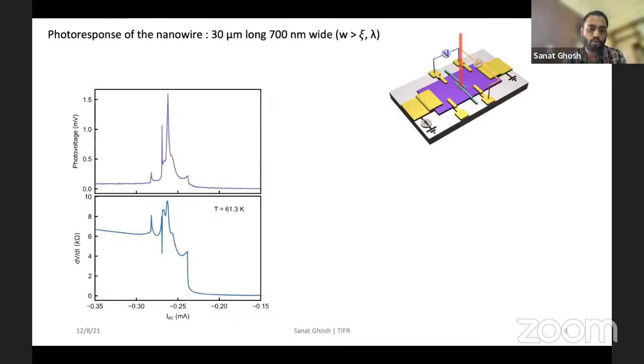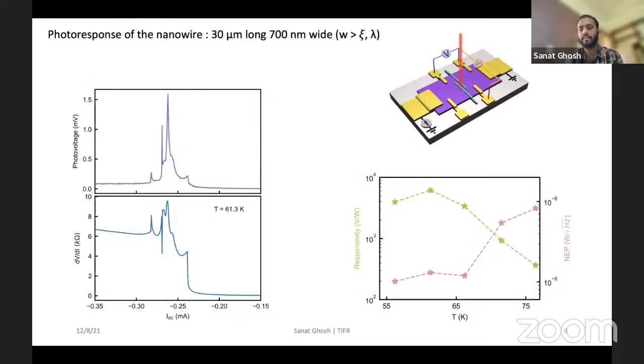Then what we do is this photovoltage measurement at different temperatures and calculate the responsivity, which is a benchmark for how good a bolometer is. This responsivity is defined as the generated photovoltage per laser power, and this shows that this is a decent bolometer, comparable to the existing ones.